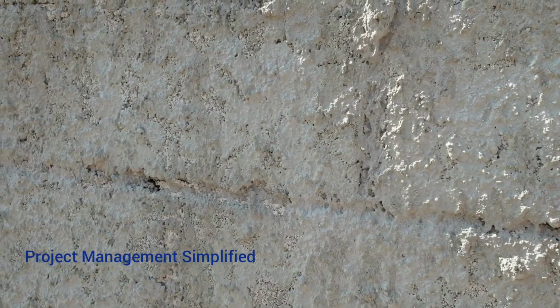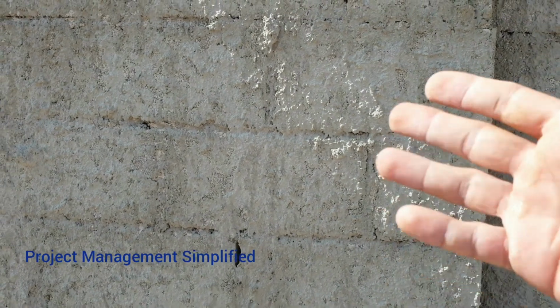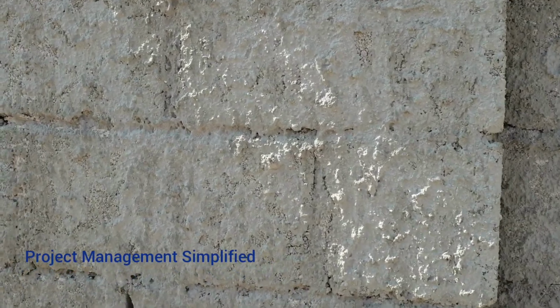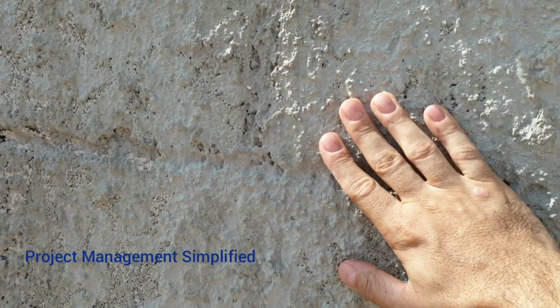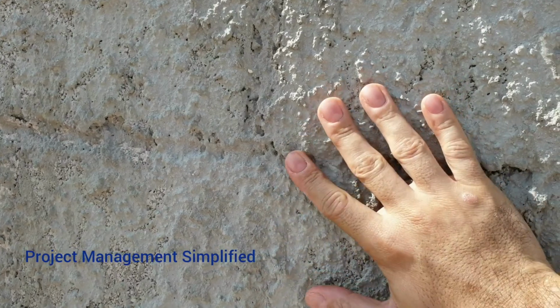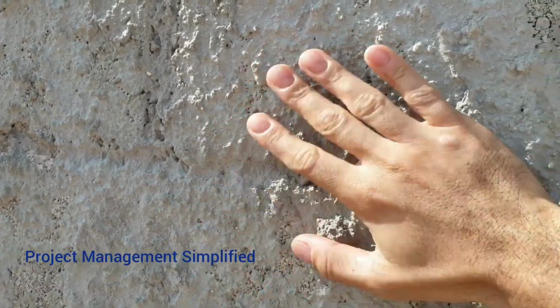It has to be half a centimeter thickness, and it has to be rough also, because sometimes when some contractors work in plastering, they just pour a juice of cement, like paint or something like that. So, as we said, first it has to be almost half a centimeter thickness. It has to be rough. It has to be strong enough, sticky. When you move your hand over this one, it will not fall.